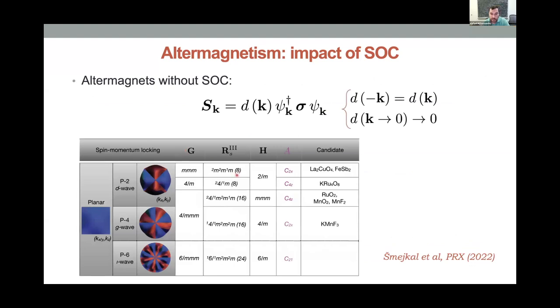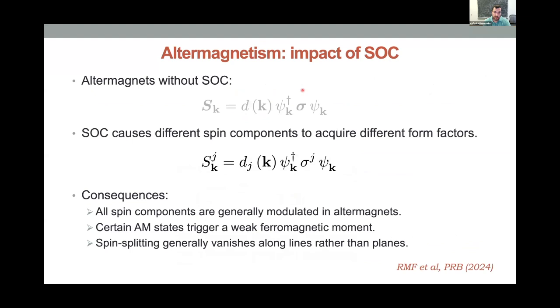So as I mentioned, right, without spin-orbit coupling, you write down the spin density as an overall d-wave form factor times the spin. But what happens when you have spin-orbit coupling, and what we showed here, and I'm going to give examples, is that different spin components will acquire different d-wave form factors, okay? This is not a summation, okay? This is just fixing a direction, okay? And what it means generically is that all components are generally modulated, and that in several cases you're going to induce a ferromagnetic moment. But the point I'm going to focus a bit more on is what impacts these nodal planes or the nodal directions under which the spin splitting is 0.